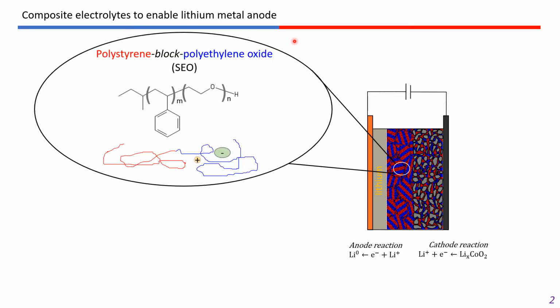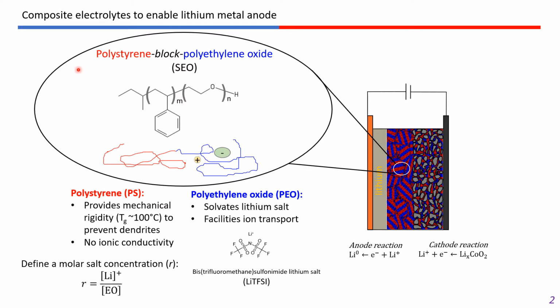In this schematic, I'm showing a polystyrene-block-polyethylene oxide block copolymer electrolyte, or SEO for short, where the two polymer blocks microphase separate into polystyrene-rich domains, which provide mechanical rigidity but do not conduct ions, and polyethylene oxide-rich domains, which solvate a lithium salt, in this case LiTFSI. And for the purposes of this talk, we'll define this molar salt concentration r, which is the molar ratio of lithium ions to ethylene oxide moieties. And in these polyethylene oxide salt-rich domains, ions are transported between the anode and cathode of the cell.